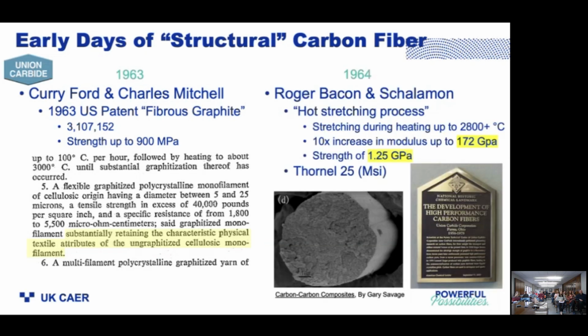The following year, 1964, Bacon and his colleagues patented what they called a hot stretching process. They took these cellulose fibers through furnaces and actually stretched the fiber while it was forming, producing a modulus of 172 with a strength of 1.25 gigapascal. Low by today's standards, but in 1964 this was the first structural carbon fiber ever produced, marketed as Thornell 25, and it went into NASA's Gemini program at the time.